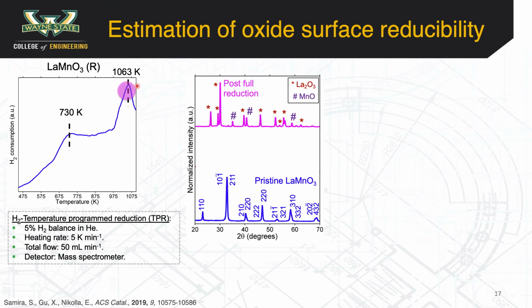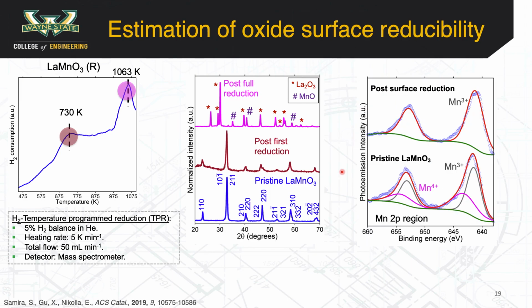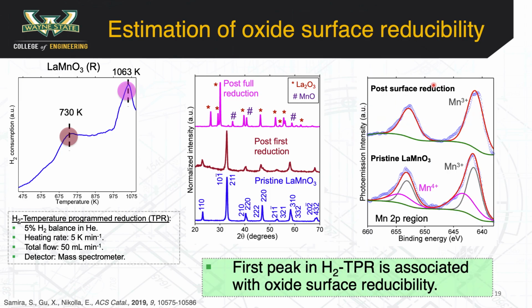If one were to stop the TPR after the second peak and XRD the oxide, it is observed that, for instance, LaMnO3 is completely reduced to a mixture of La2O3 and MnO. While if one were to stop the reaction after the first peak, the bulk crystal symmetry is found to be intact using X-ray diffraction.